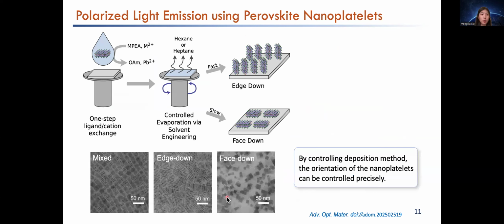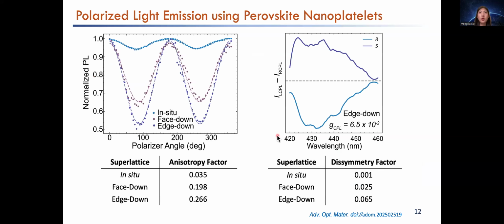And furthermore, we want to find a way to orient these materials, because once we orient these nanoplatelets, we can align their electrical dipole moment. If we get them fully standing on the substrate or make all of the nanoplatelets lie on the substrate, we will have an even stronger linearly polarized light. This allows us to get a very large, enhanced anisotropy factor when we orient all of the nanoplatelets from mixed orientation to face down or edge down orientation.